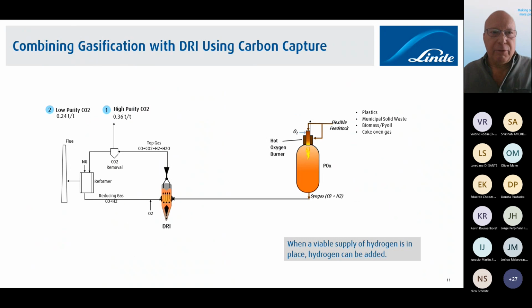And for the sake of combining the last slides I showed, we can of course have gasification and producing direct reduced iron, and also having a carbon capture of that. So there are alternatives around here as complementaries to just going directly into hydrogen steelmaking. And that could be similar in other industries as well. And that could also nicely connect to a circular economy. The beauty of some of this is that it's easier to fit in with the existing production structure than going directly into hydrogen. And of course, we can phase in the use of hydrogen into these processes very nicely.